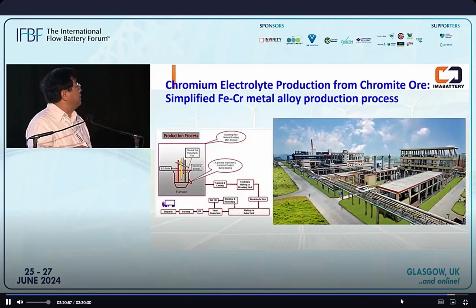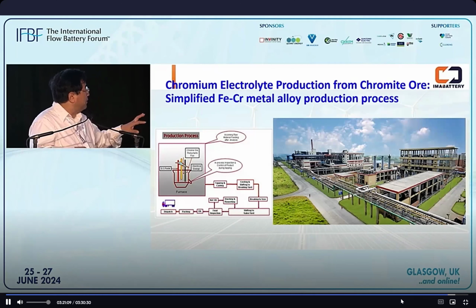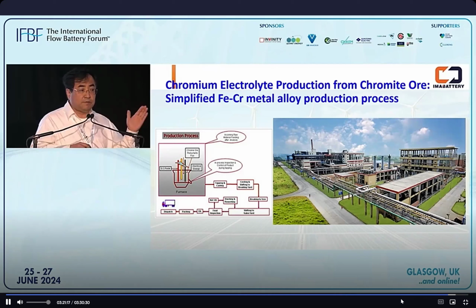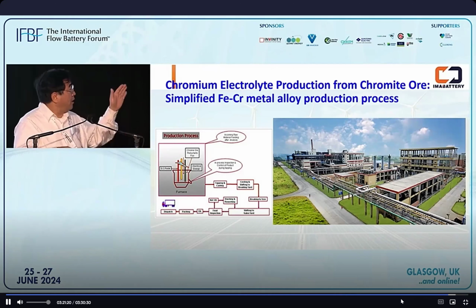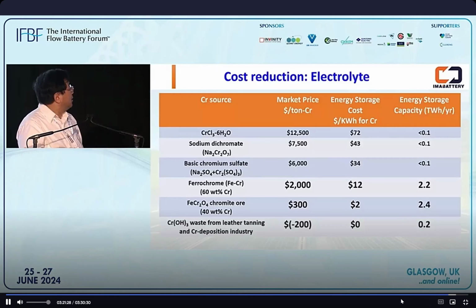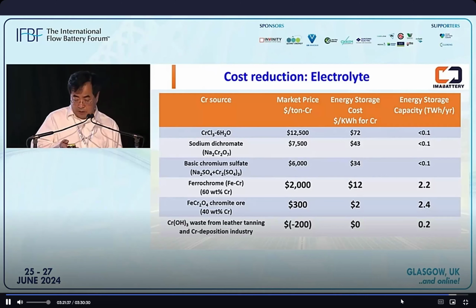Actually, we can do even better. For the iron chrome metal alloy, when you take the chromite ore and just mix it with carbon, you can reduce it. All the way to the metal alloy there are a lot of steps, and only 1/3 of the steps are useful in terms of electrolyte manufacturing. So we are working with our licensees and other partners to try to use the chromite ore directly. If we can use the chromite ore, the price can be even lower, a couple of dollars per kilowatt hour.